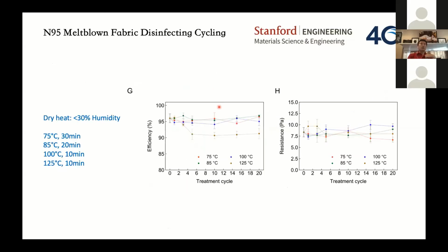And then we look into the dry heat further, right? For the dry heat we now do 75, 85, 100, 125 degrees, for different amounts of time. So 125 is too high, the efficiency dropped to about 90%. And below 100 degrees Celsius, dry heat looks reasonably safe. We got 20 cycles of treatment right there. They look good. Air pressure drop is more or less similar. You don't really damage your N95 filtration fabric that much.